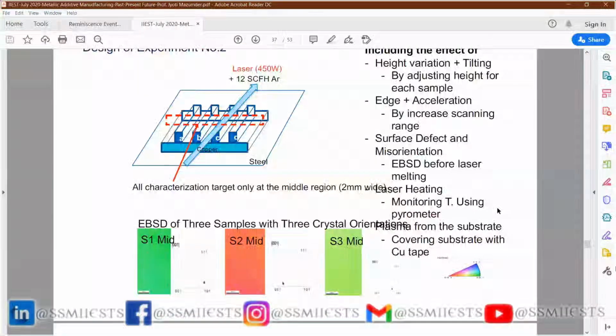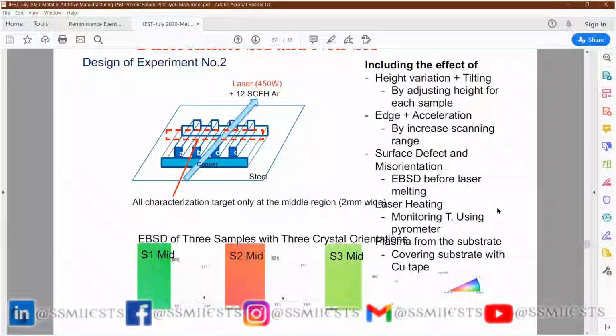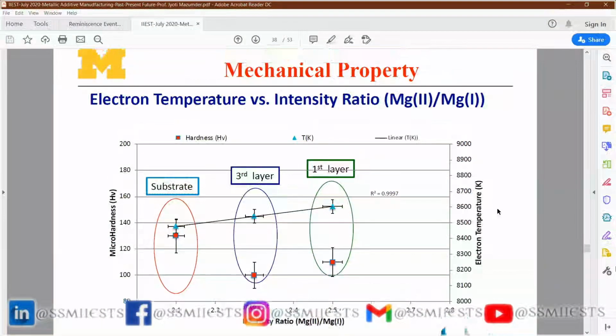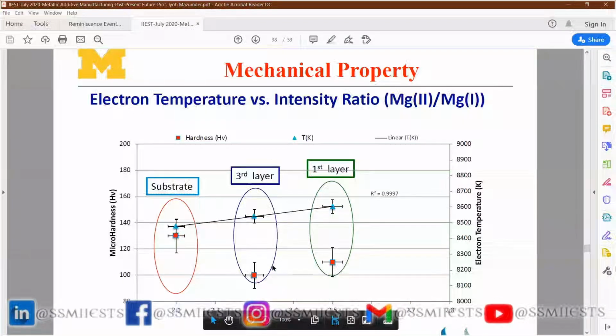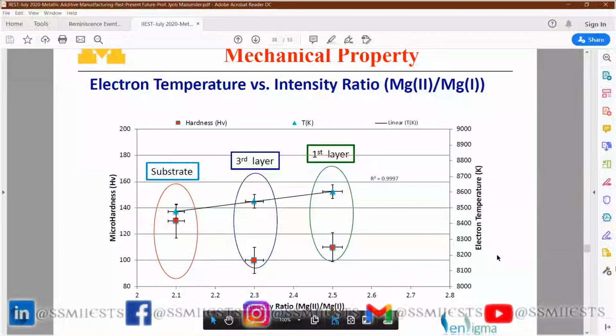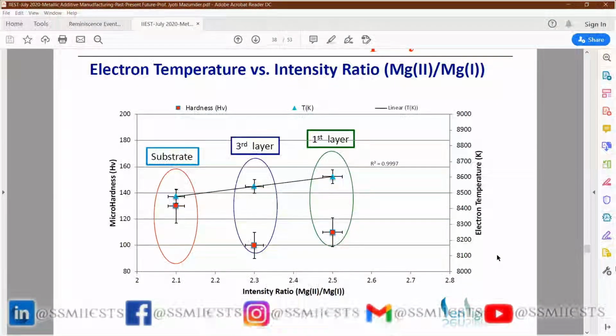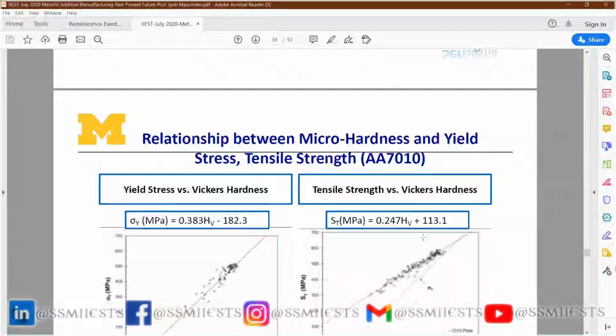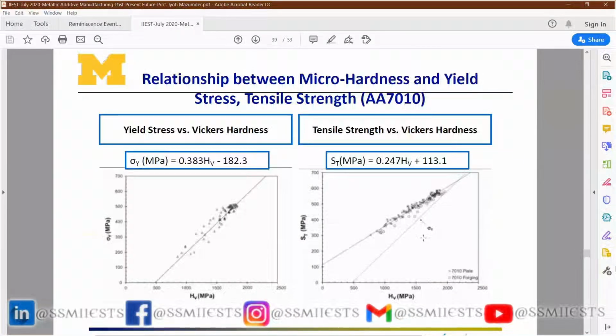And if you take the electron temperature versus intensity ratio of different material, you'll find it slightly changes layer by layer. So essentially, by calculating and estimating the ratios of this, we can also find out what is the micro hardness. So not only are we looking at the composition and the defect, now I am getting into mechanical property. The details of this I'm not going to go into. What we found out is, if you especially take the ratio of the magnesium 2 and magnesium 1 line for aluminum alloys containing magnesium, this intensity ratio started giving me mechanical property.